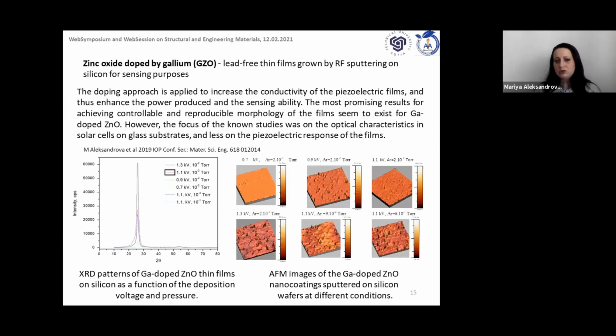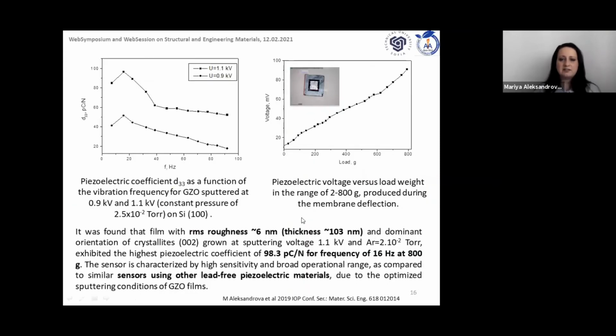The same approach we used to optimize zinc oxide doped by gallium. The function of the doping element is to increase the electrical conductivity and in this way to gain further generated electrical power without distracting the piezoelectric properties and polarization effects. Here I also provide the different AFM images to compare the roughness of the surface and how it further affects the piezoelectric coefficient.